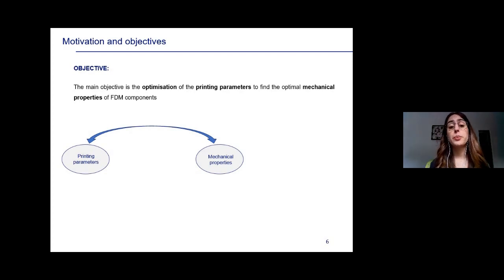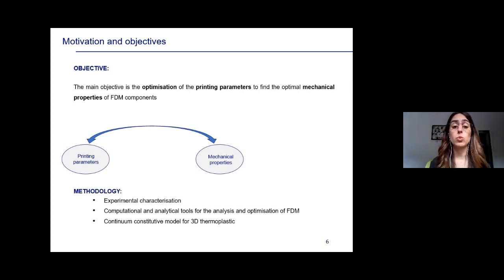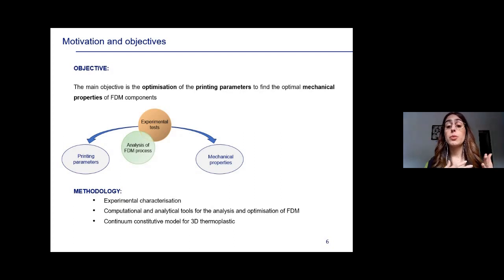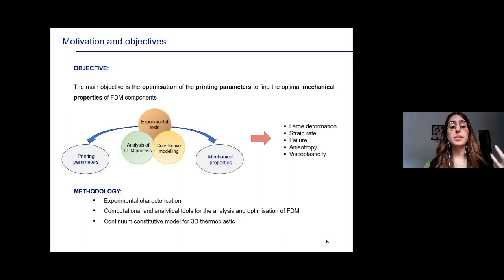And to find this link between the printing parameters and mechanical properties, we developed a methodology with three different parts. As I said, the objective was to develop different tools to help us in the optimization. But first of all, we carried out an experimental characterization in which we analyze the influence of the most relevant printing parameters. Then we propose different tools to reproduce the 3D printing process and to understand it. And finally, with all the observations, we propose a new constitutive model. I would like to also say that this link between printing parameters and mechanical properties was done taking into account that these materials can present large deformation and strain rate dependencies.